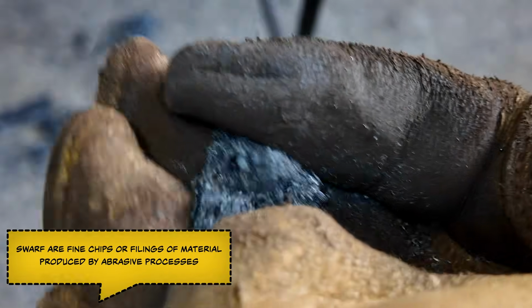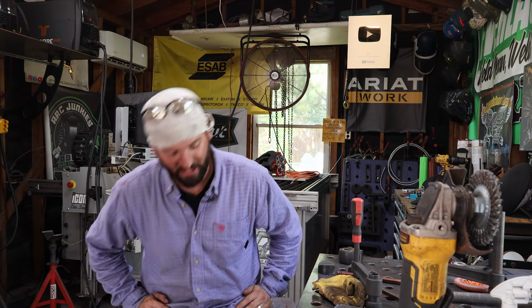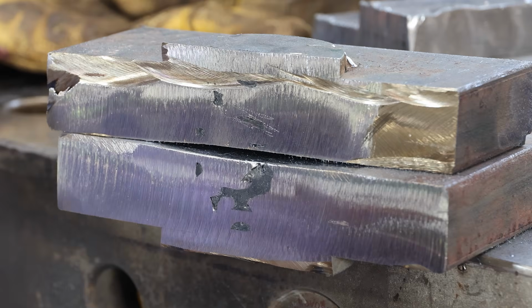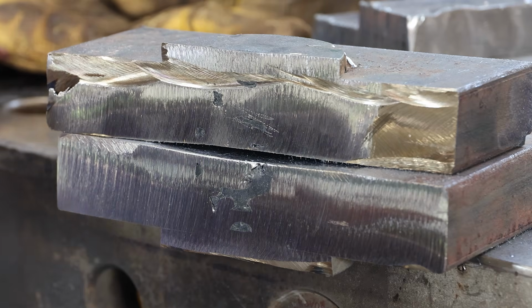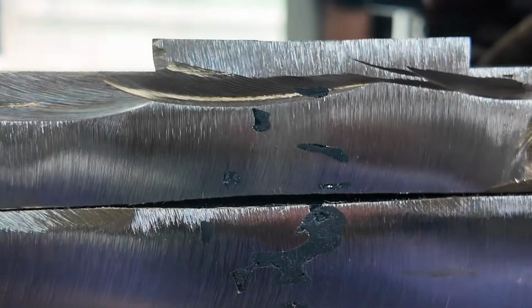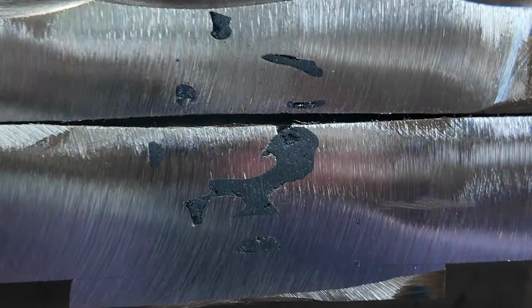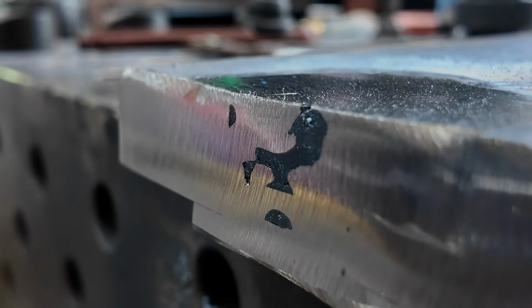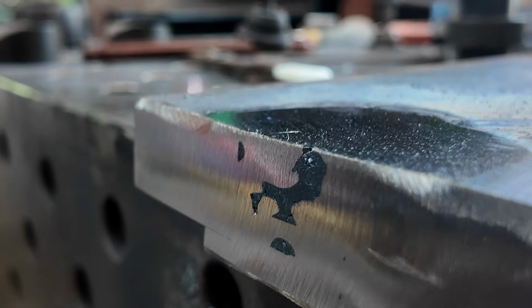It makes swarf, which is small, fine metal shavings that are heavy enough to just sink to the ground. And now that we've got the face of everything cleaned up with that fiber disc, we can see everything a little bit clearer. The 1-inch plate with the 1.5-inch hole trapped a ton of slag. Maybe that rule of thumb, that hole being 1/2 inch smaller than the recommended 2-inch hole size for that plug weld, for that thickness of metal, maybe that was the issue.